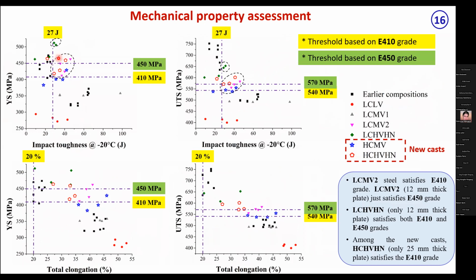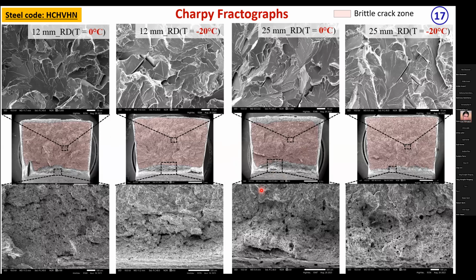All these results are satisfying at least the 410 grade. Yellow color represents the 410 grade requirement, and green is the 450 grade. So in many cases, we are exceeding the 410 grade and 450 grade, as I will show in the conclusion section also. Fractography study has also been performed, and as expected, there is some amount of ductile fracture. These are the minus 20 tested specimens, 0 and minus 20. Even there, we have found some amount of ductile fracture before the cleavage fracture happens.